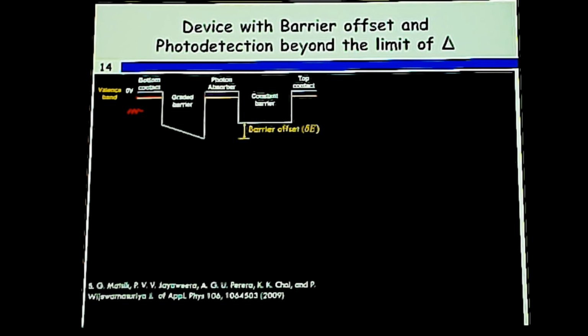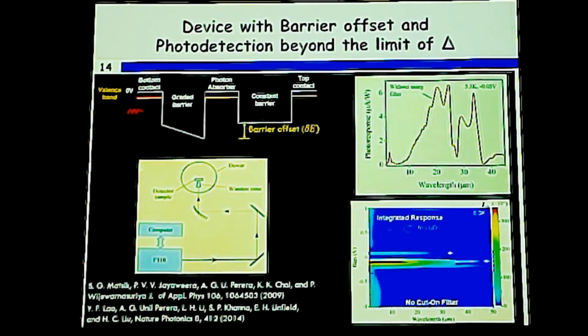But in this device, not only the mid-infrared, actually the photoresponse was observed much farther away than the mid-infrared. So that is beyond the limit of the split-off. The limit of the split-off is mostly here in the mid-infrared region. However, the photoresponse is much farther out than that limit. So this is the extended wavelength photoresponse, recently observed and published in 2014. This kind of extended wavelength photoresponse shows very interesting properties.